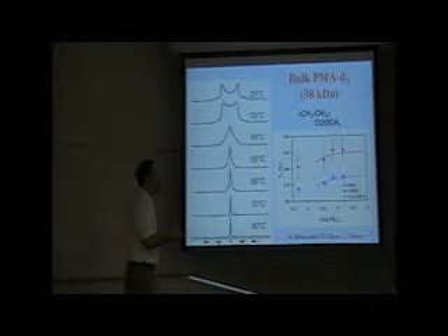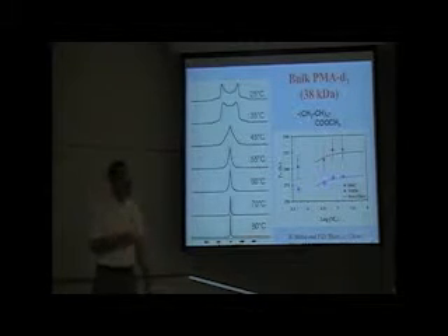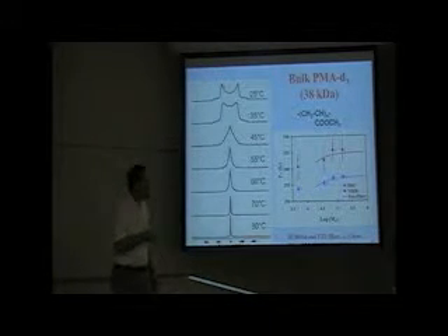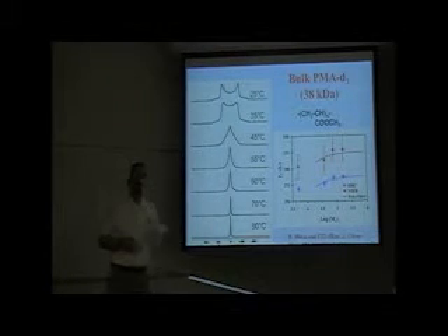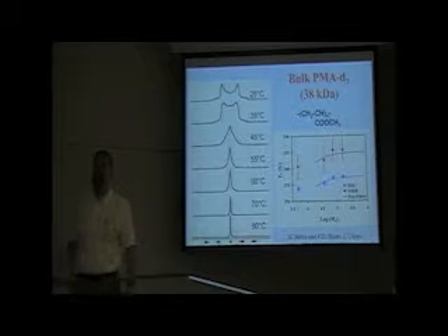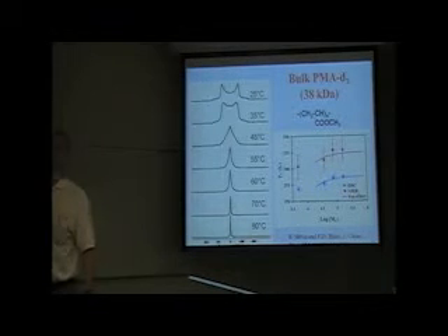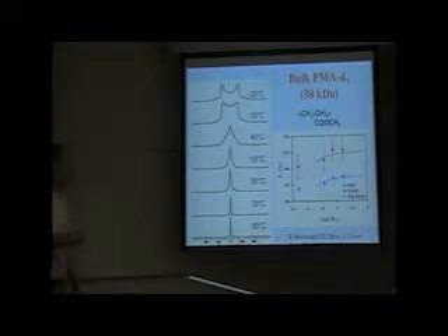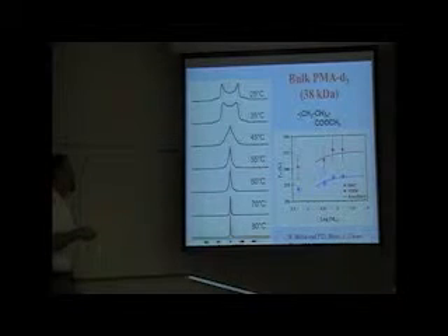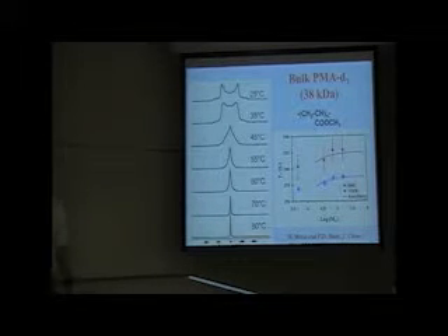Okay? So I can measure this with calorimetry, and it turns out that there's a dependence on polymer molecular mass. And these are not error bars. These are the sensitivity of the experiment. This is when I start to see that a glass transition is starting, and this is when I see that it's ending. And I can measure the same thing with NMR. It's a heck of a lot more expensive, but this represents the sensitivity. 20 degrees below where the glass transition temperature starts, I can see that there's stuff going on there.